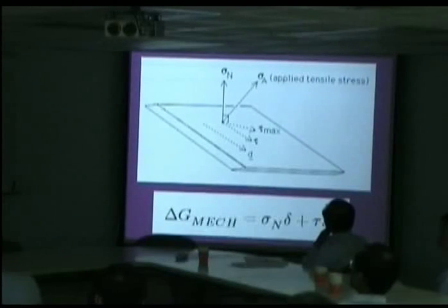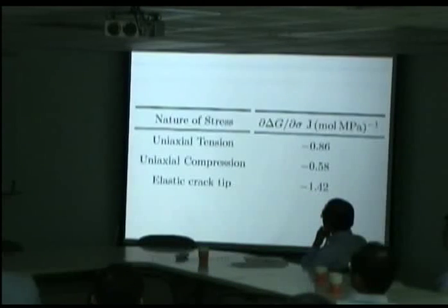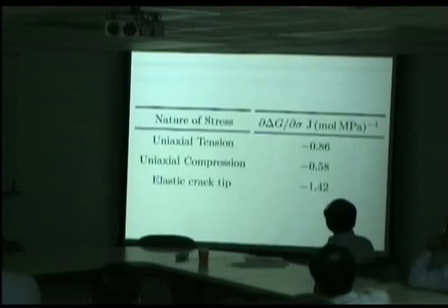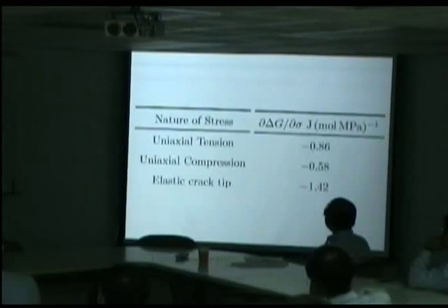So this is why we can stimulate martensite to form above the MS temperature, because we have a mechanical driving force which is stimulating martensite. And that mechanical driving force is different depending on the state of stress. So when you have uniaxial tension, it's the largest effect, because that tension favors shear, and it's along the direction of the volume change. When you have uniaxial compression, the volume change opposes the compression, but the shear is exactly the same as in tension. And then you can have more complicated effects with multi-axial stresses.